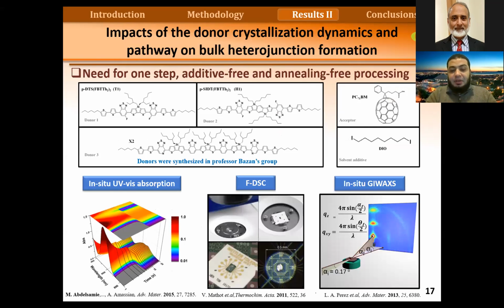So we tried to use different in situ techniques. We used in situ absorption and also in situ X-ray diffraction. And we also combined this with flash DSC, where we try to crystallize the material from the melt very quickly and see what's happening.